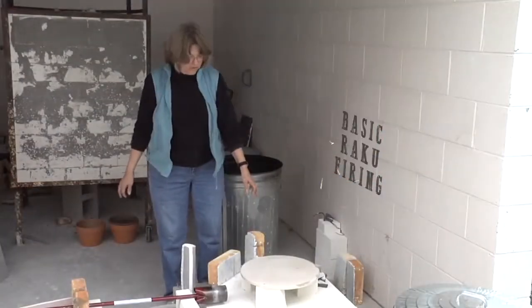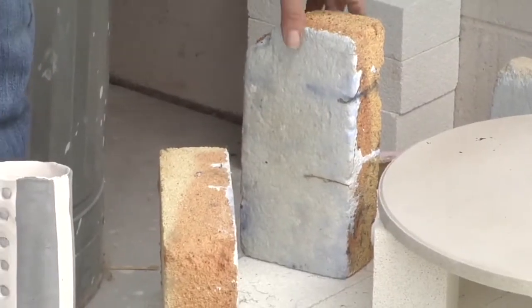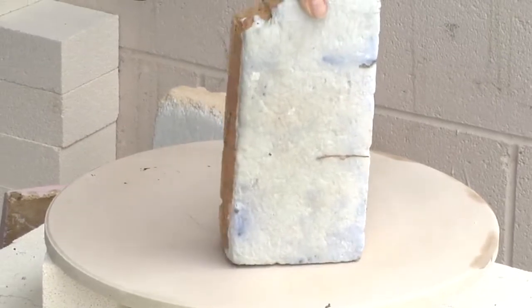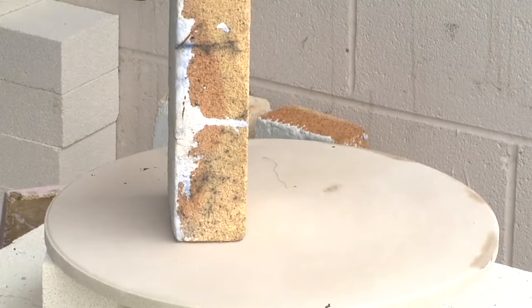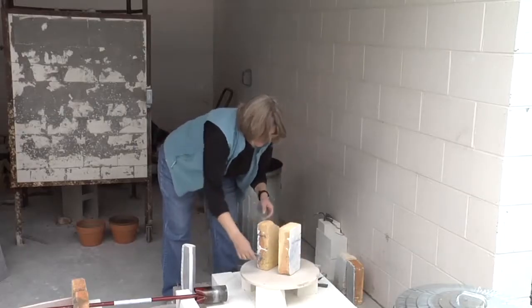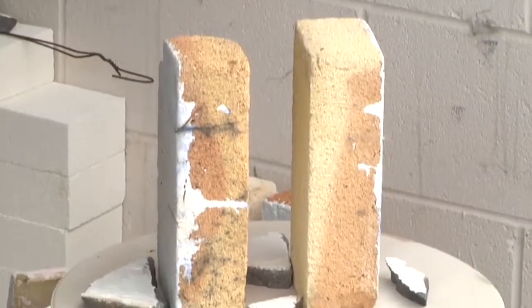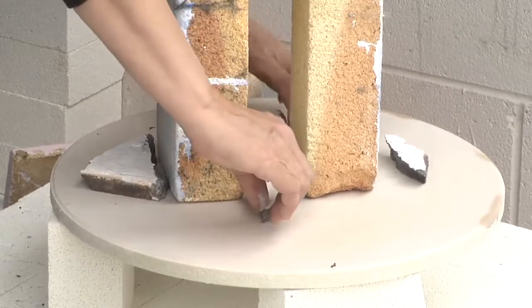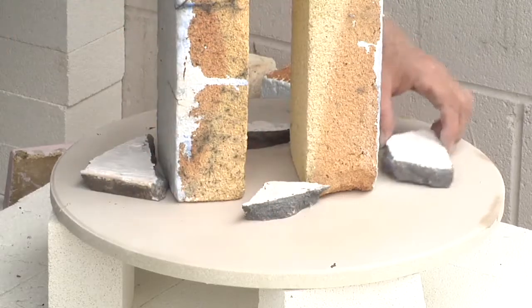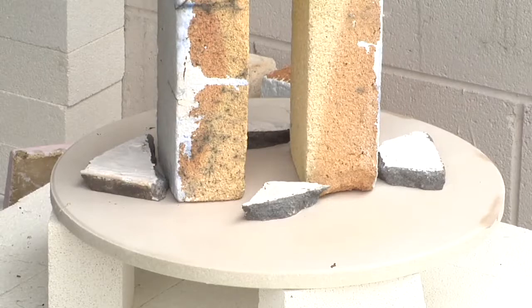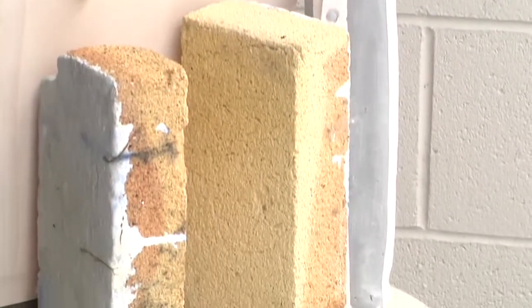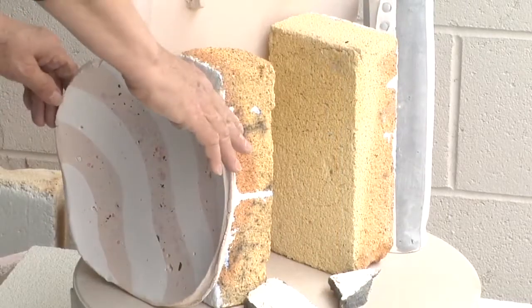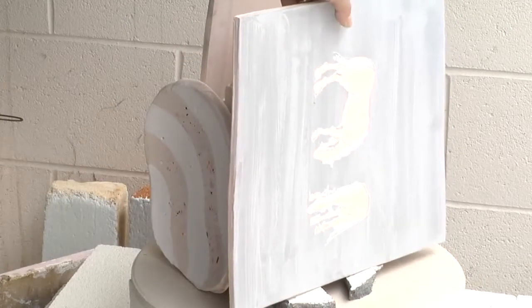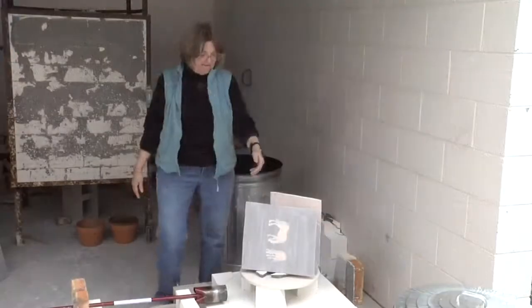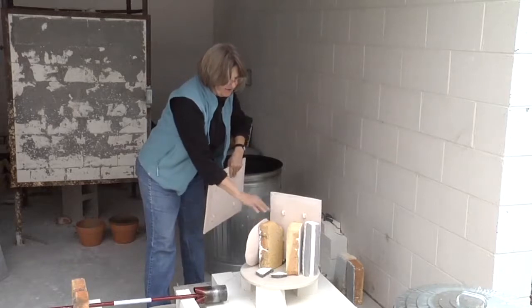Okay, so I'm ready to load up for raku firing, and I have a couple of slabs and some other pieces, and I like to fire the slabs leaning against bricks. So I'm going to load them up like this. There is a nice coating of kiln wash to protect it from the glaze. I'm putting these up so that there's not a flat line of a barrier for the flame so that you can get heat under the pieces. Okay, so I'm going to start loading up the slabs, and it's kind of a narrow kiln. Okay, so I have 4 pieces in here, 2 slabs and a dish and a cylinder.